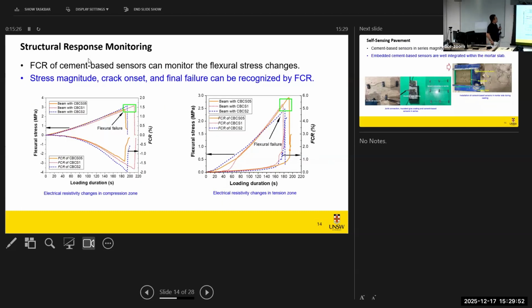During the test, the FCR, the fractional change of the resistivity of the cement-based sensors, can monitor the changes of the flexural stress during the loading. Secondly, the stress magnitude and the crack initiation can be recognized by the gradual increase of the FCR, or the decrease of the FCR, in terms of compression and tension. And finally, the rapid jump of the FCR can be captured at the final failure of the mortar beam.